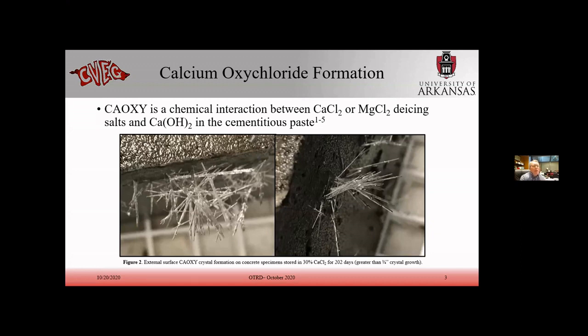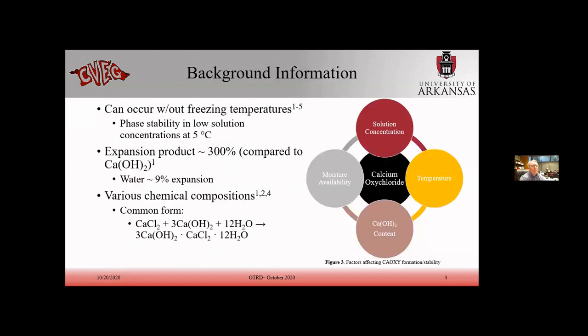So anyway, here are some pictures that Casey took of some of the calcium oxychloride that had formed on the surface of some modulus of rupture specimens. They measure about 3/4 of an inch in length. This calcium oxychloride can occur without freezing temperatures, around 5 degrees C. The expansion product can be roughly a 300% increase in size, whereas when water freezes, it's about a 9% expansion.